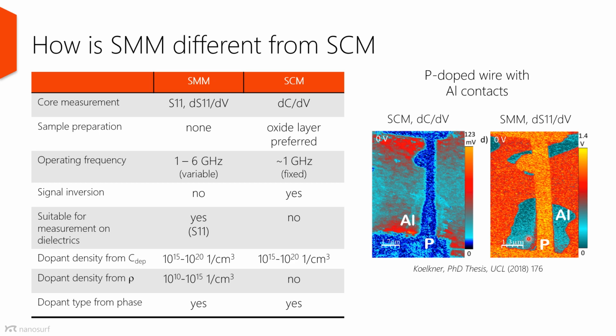If we look at the comparison between the two modes in the table, the SMM has several advantages over the SCM. So first, the SMM has two operating modes, the S11 and the DS11DV mode. Both have their advantages and their areas of application. The SCM has only the DCDV mode. In terms of sample preparation, the SMM is more forgiving. The SCM works best with the oxide layer. In operating frequency, SMM has variable operating frequency, the SCM is fixed. There is a signal inversion in SCM which does not happen in SMM. In S11 mode, the SMM could be used for measuring the dielectric constant. The SCM cannot do that.